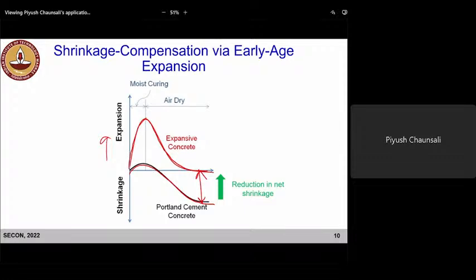It could be 400 microstrain, 500 microstrain, 600 microstrain, depending on your type of concrete and also the environment. But by inducing this expansion, we are able to compensate. You can manipulate this expansion so that you can either have net expansion, or you can just compensate. You have close to zero shrinkage. So there is a reduction in the net shrinkage. That's what we mean by shrinkage compensation. So that's very advantageous when we want to develop a concrete which will prevent shrinkage cracks. Okay.